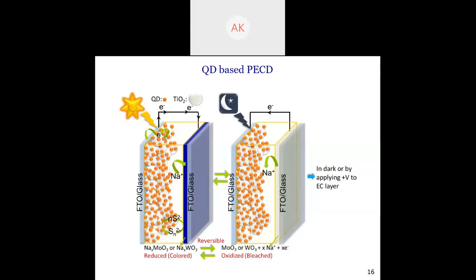and it gains the deep blue color. Now it is a reversible reaction, so under dark the opposite starts to occur, or you can also apply a positive voltage to the electrochromic layer. Then the WO3 releases the Na+ ions into the electrolyte and also releases the electrons to get oxidized. And finally, you get the bleached state. This is the bleached state, whereas in the reduced form, it is the colored state.